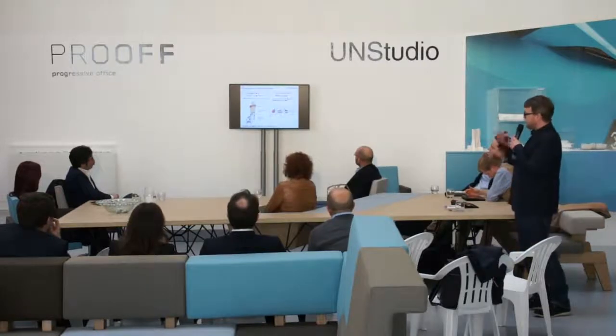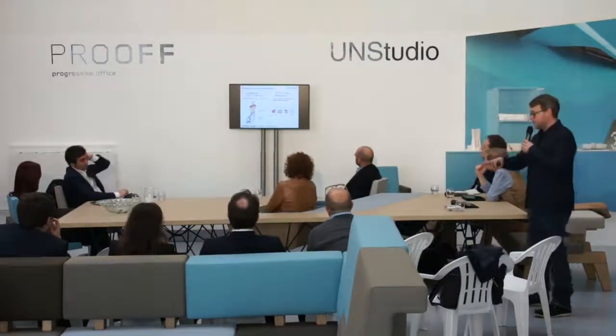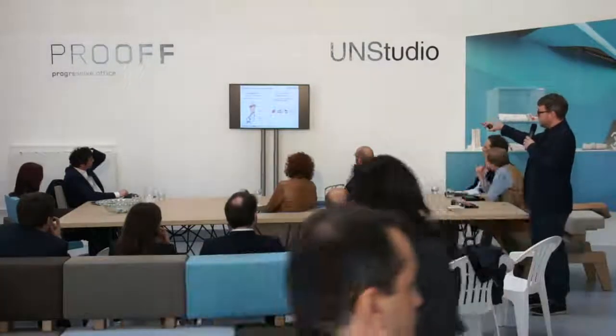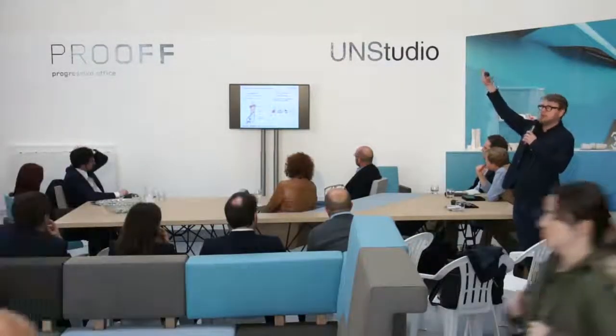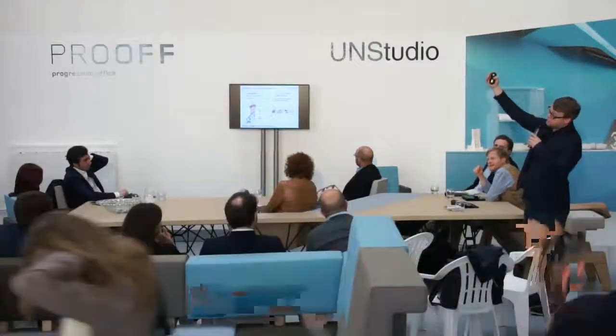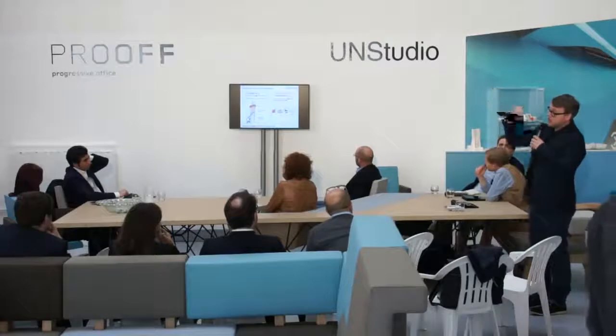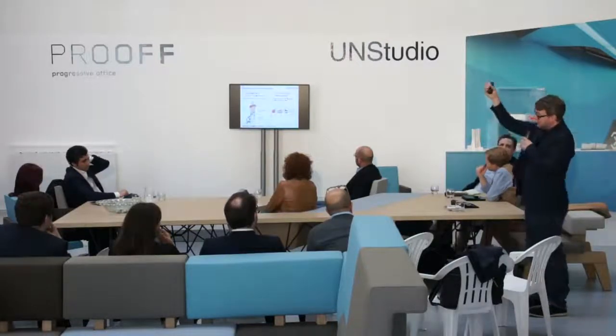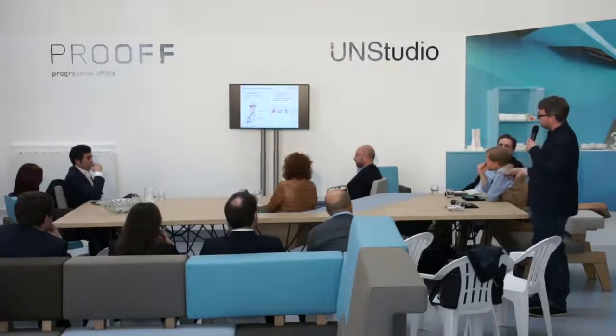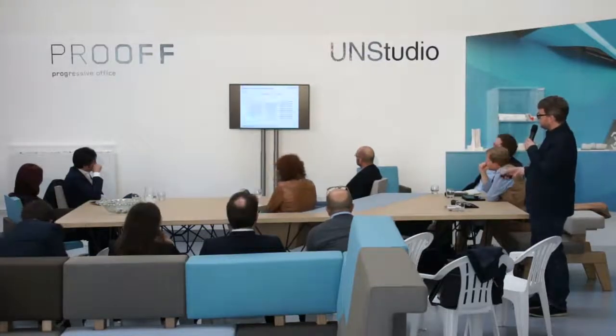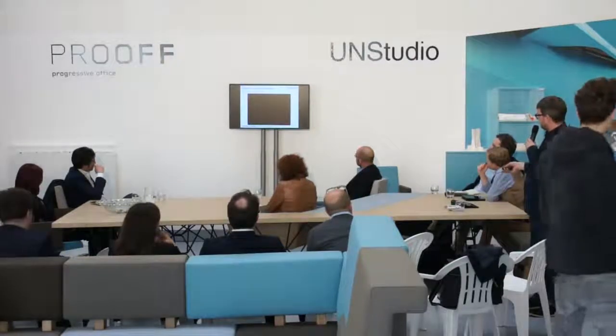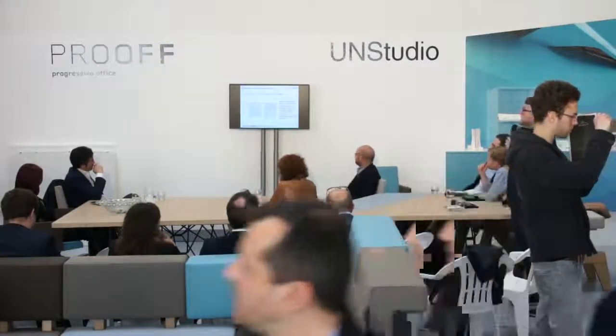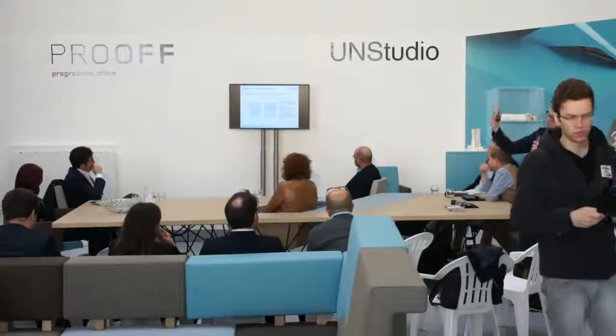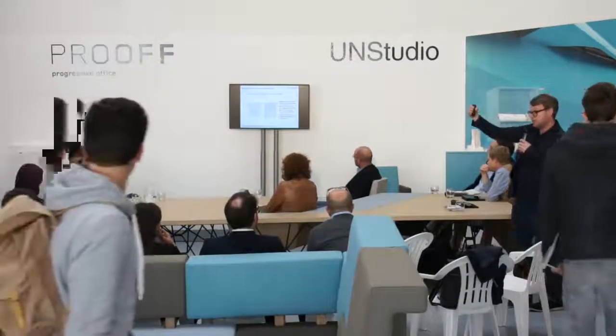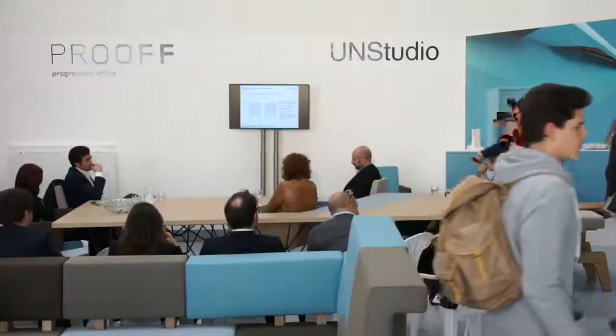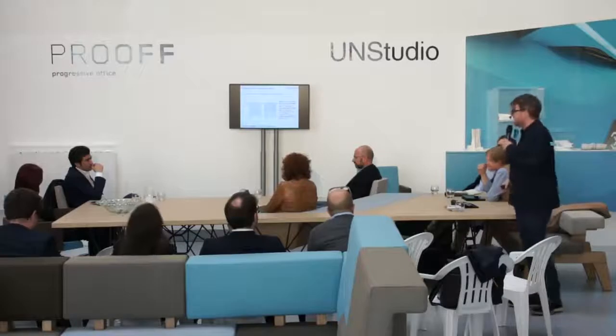How is it made? It's made in a very different way from normal glass. Normal glass is floated out on a bed of tin on a float line, whereas fusion glass is in fact formed in a vat about that high up in the air, and the glass flows vertically down without touching tin or touching any impurities. And by doing that, it fuses in itself as it drops through air and cools. I won't go through this little video which explains it. As it collects, it's then sliced as it drops through, but it's very thin. In fact, it's so thin you can now roll it up into a big roll, like a piece of paper.